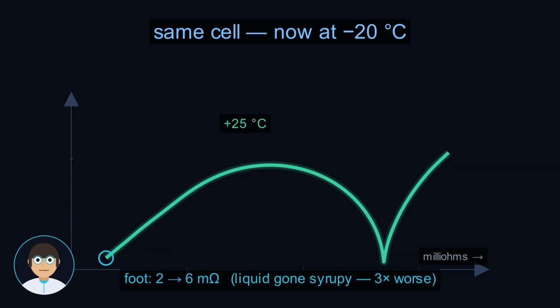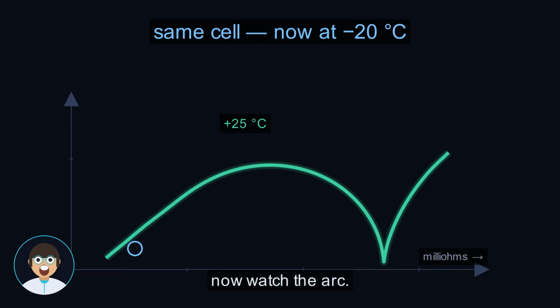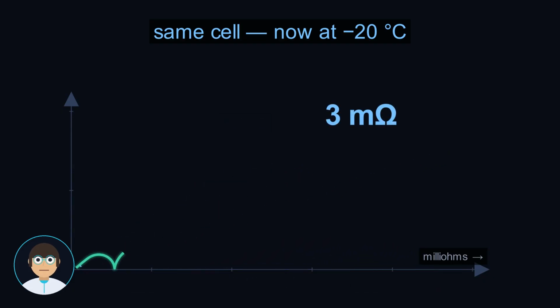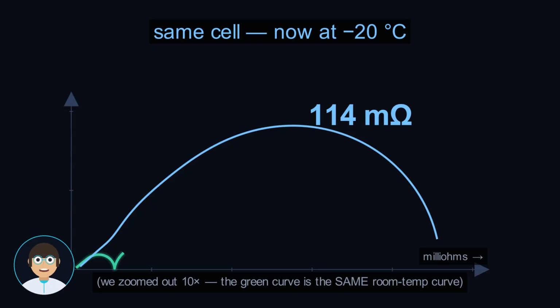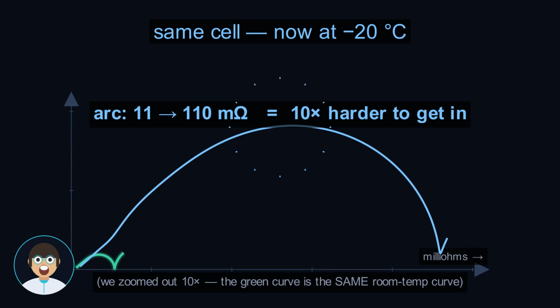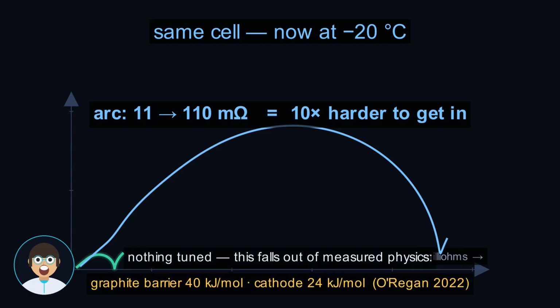Watch the foot first. It slides right from 2 milliohms to about 6. The liquid inside has gone thick and syrupy, so every ion swims slower, 3 times worse. Annoying but survivable. Now watch the arc. It does not grow, it detonates. 20, 50, 80. We have to zoom out 10 times just to keep it in the frame. 110 milliohms. The exact step where charge enters the electrode just got 10 times harder, and we did not tune anything to get this. It falls straight out of activation energies measured on this cell and published, 40 kilojoules per mole at the graphite side.